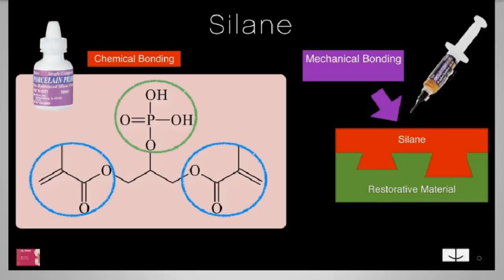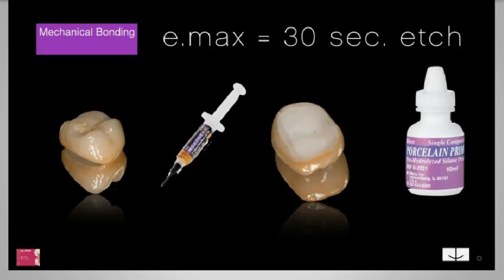It works in two ways, both in a chemical nature and in a micromechanical nature. In the micromechanical bonding, that is what the hydrofluoric acid etch is for. The hydrofluoric acid etch creates this pattern inside of the ceramic where the silane can flow into. Now, different glass ceramics require different etch times. The old glass ceramics used to require 90 seconds, they would say up to 120 seconds of hydrofluoric acid etch. For Emax, that's actually much different. It is only 30 seconds.